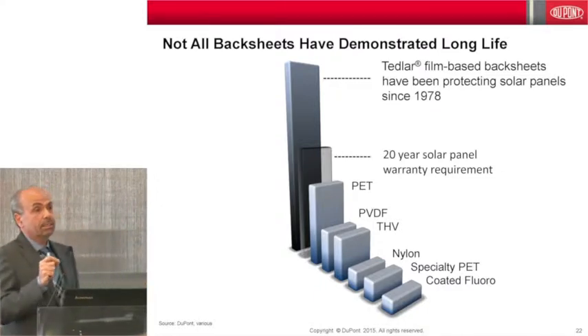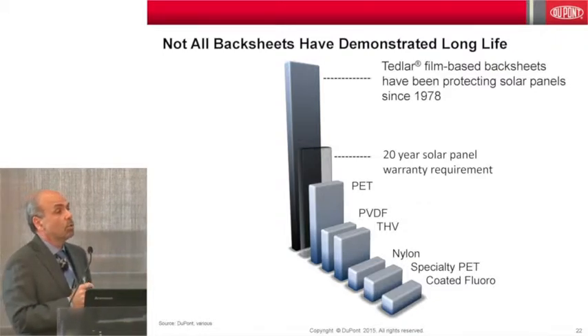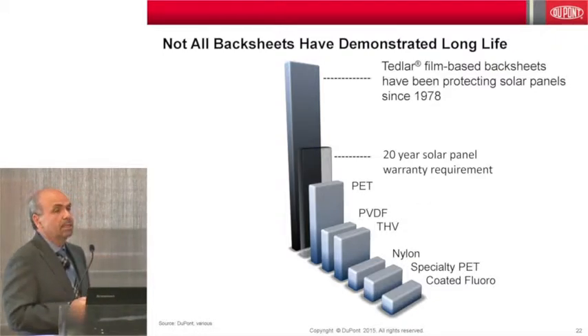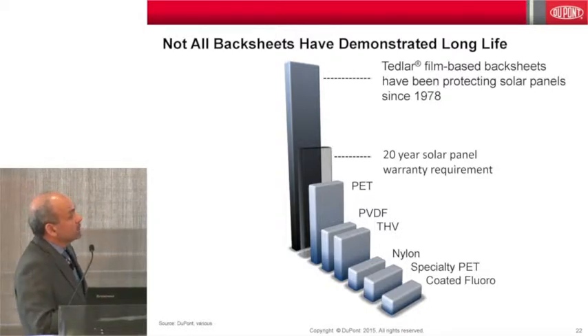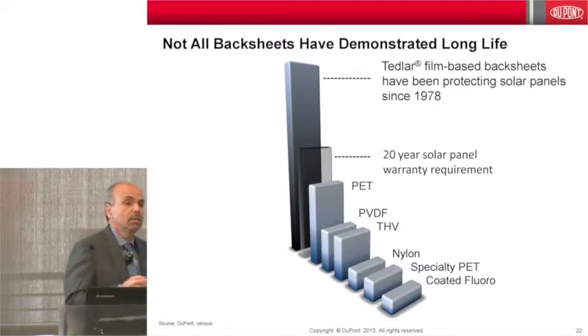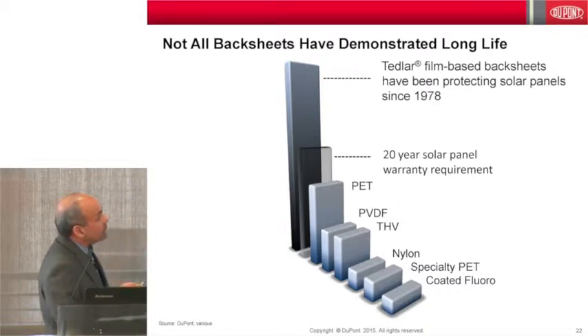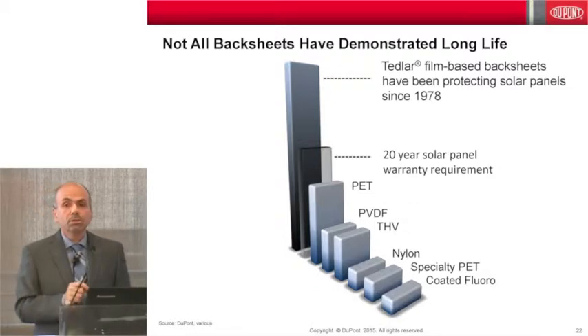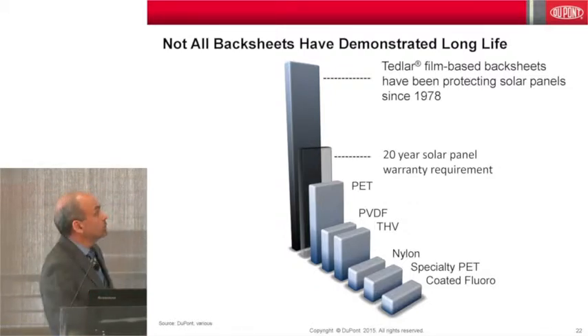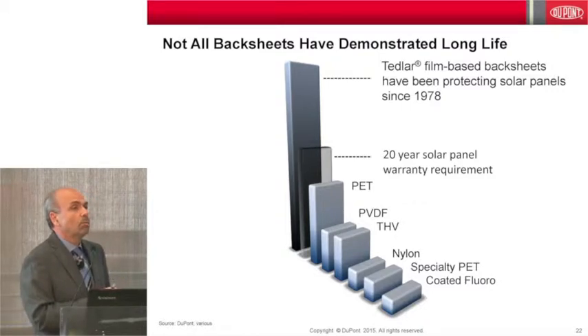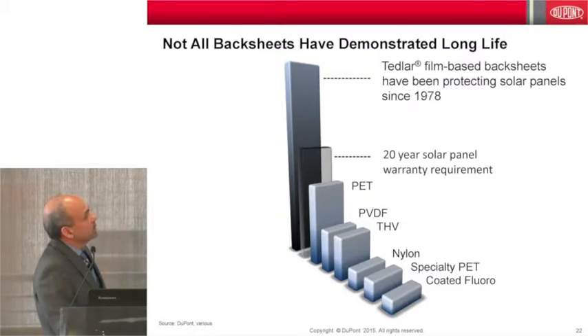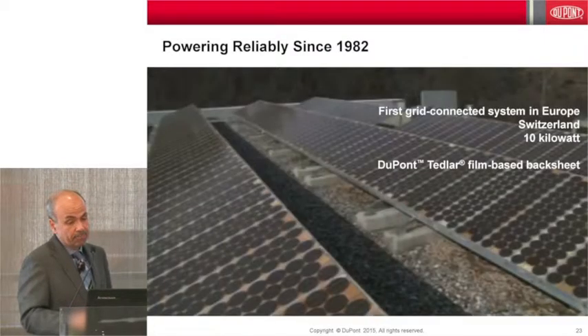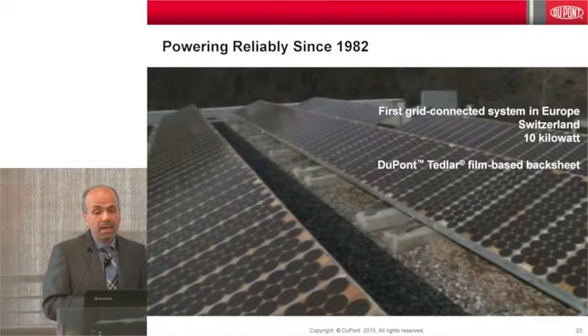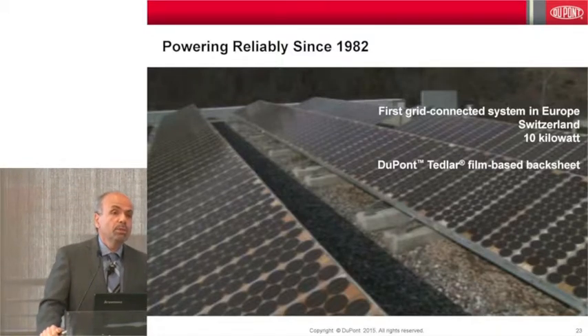The Tedlar-based backsheets is the only solution out there that has been in the field for more than 40 years. We have a proven history. And of course, this is a great area to be. And for that, there are a lot of different approaches. Many different polymers can provide backsheets, but they don't have the track record that Tedlar has. Just keep in mind that the minimum warranty that you need for your modules is 20 years. And we have examples where Tedlar has been used out in the field for more than 30 years, where what you see there with the acronyms are different classes of polymers that provide backside protection, but they don't have the track record as Tedlar. And these are photos of panels and fields that use DuPont materials backsheets.